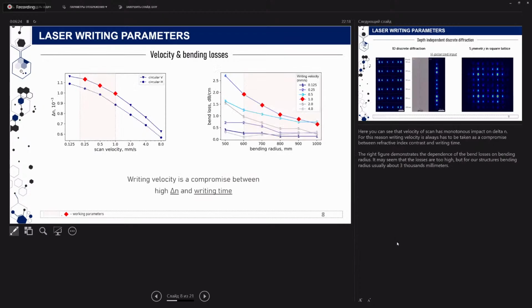Here you can see the velocity of scan has a monotonous impact on delta n. For this reason, writing velocity always has to be taken as a compromise between refractive index contrast and writing time. The right figure demonstrates the dependence of the bend losses on bending radius. It might seem that the losses are too high, but for our structure, bending radius is usually about 3,000 millimeters.